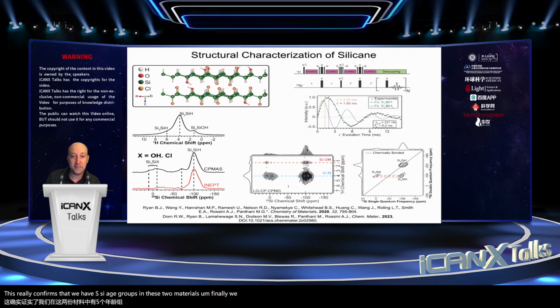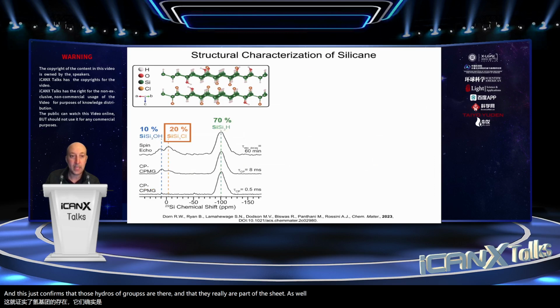Finally, we have this 2D proton-silicon dipolar heteronuclear correlation spectrum. And this just confirms that those hydroxyl groups are there and that they really are part of the sheet as well. Okay, so we already saw this data. This was our quantitative silicon-29 NMR spectrum that suggests about 20% of these silicon atoms are chlorine terminated.